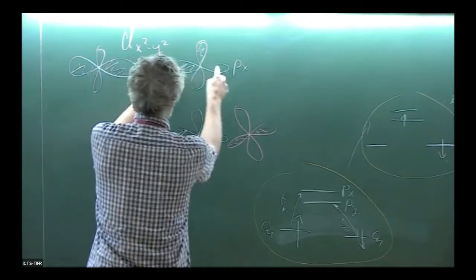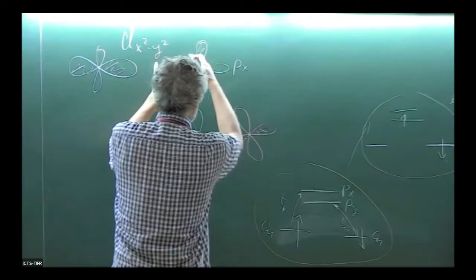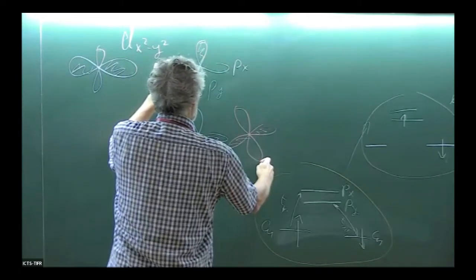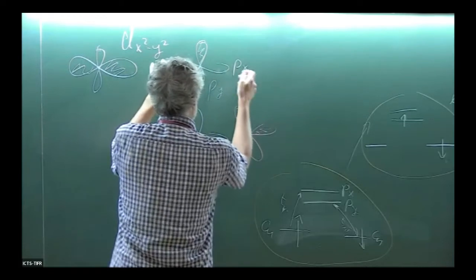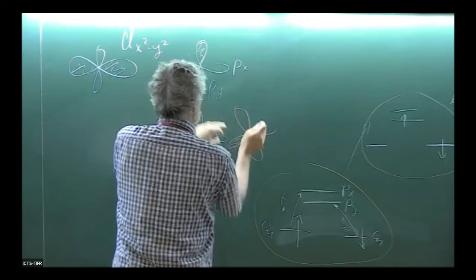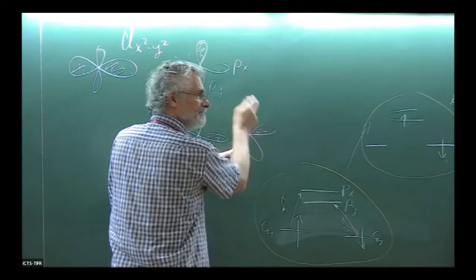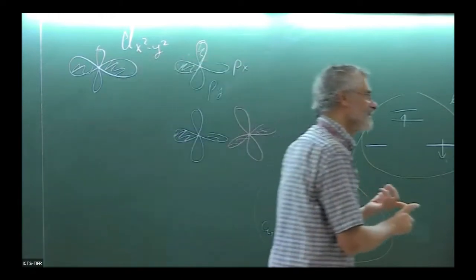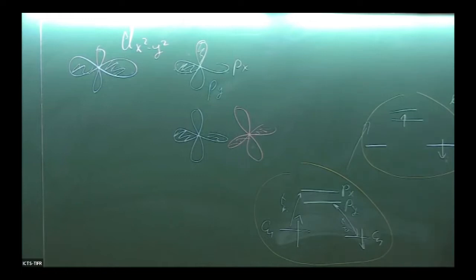In that case, we hop here, and this mirror symmetry is lost. So there is a possibility that this electron hops further to the copper side and back. So we have a combination of superexchange and this 90-degree ferro exchange. So depending on the angle, one can very finely tune the J's from antiferromagnet to ferromagnet. Right, good. Okay, this was the 90-degree exchange.